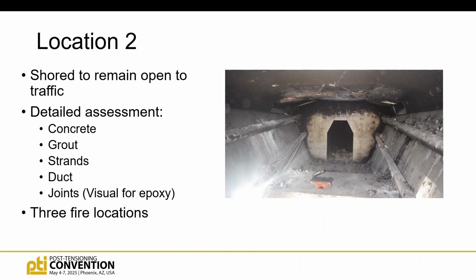Now, we have a fire protection unit in WJE, and we're very fortunate to have those guys. And so I showed them some of these pictures, and they were able to walk me through where the fire was hottest, where versus it was not quite as hot. And basically they said that this condition here, where it's really a white colored or concrete colored appearance, that's where the fire was hottest. It had less soot. And if you can imagine, if you've got a fire pit in the backyard, as the fire begins to go out, it generates more smoke, hence more soot. So the hotter the fire, the less soot you have.